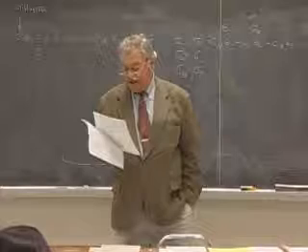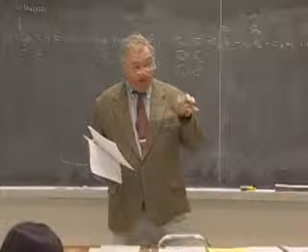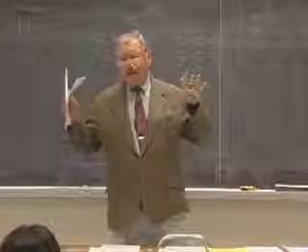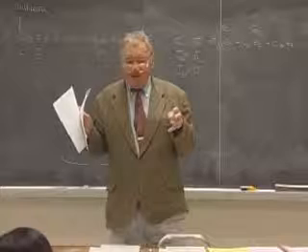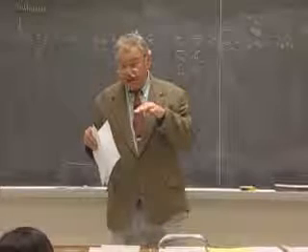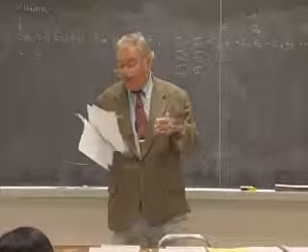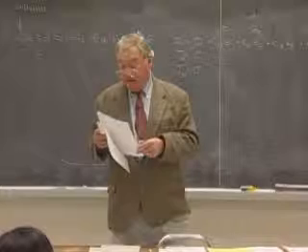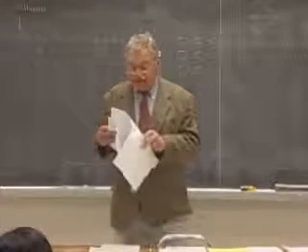So it is a mess, and these are rules that you have to bear in mind if you're ever going to go from matrix form, which works absolutely lovely in a fixed coordinate system. But if you have a single crystal and you want to refer it to different axes, you have to be prepared to resurrect the full tensor form, and then and only then can you work symmetry transformations.